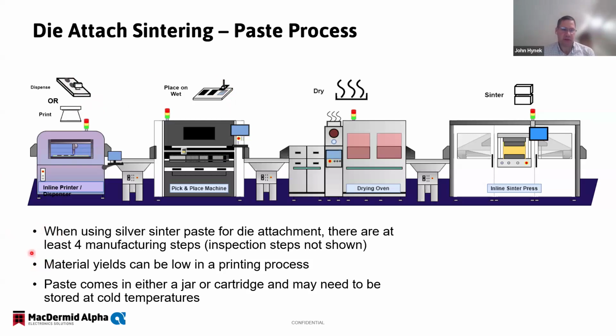One of the biggest drawbacks to the operation is that material yields can be low in a printing process. We've seen in our labs, we're lucky to get about 70% yield. In fact, it's even lower. And then the other feature you have to take into consideration is that paste typically comes in either a jar or cartridge, and it may need to be stored at cold temperatures. So you have to have your cold storage, and you have to be able to manage either the jars or the cartridges. And one of the drawbacks to both is that silver is obviously a very expensive material. You want to be able to use as much as you can, so you have to figure out a way to extract the maximum amount of paste from the container that it comes in.